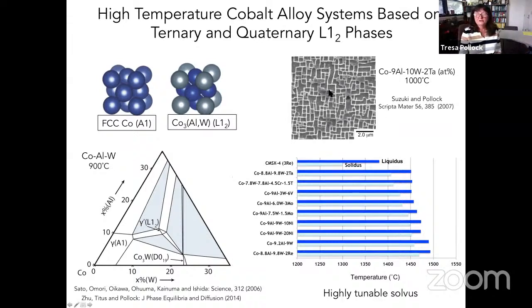These alloys look similar to current nickel-based superalloys, but have somewhat higher melting temperatures and very different properties with regard to solidification. And particularly important is they have a highly tunable solvus for these precipitates, so the temperature at which all the precipitates go into solution.